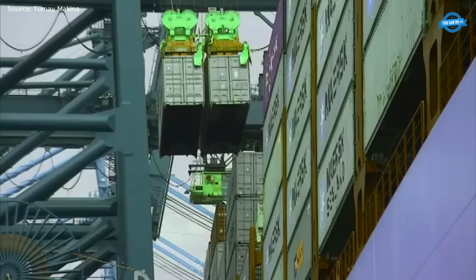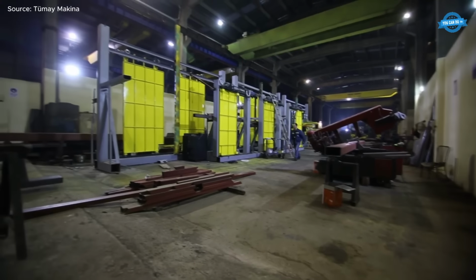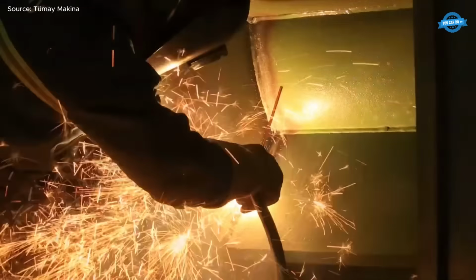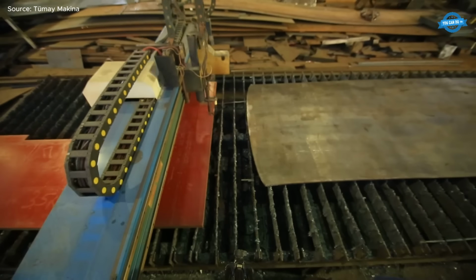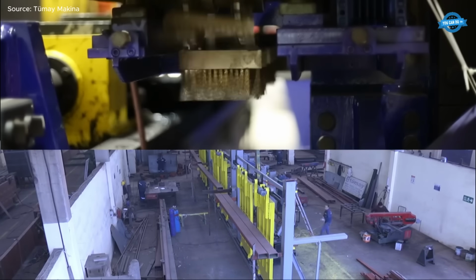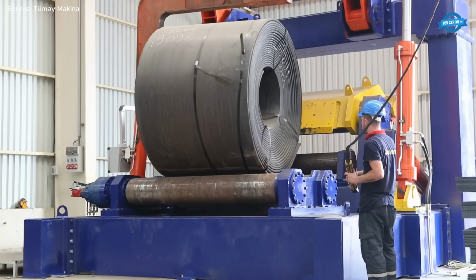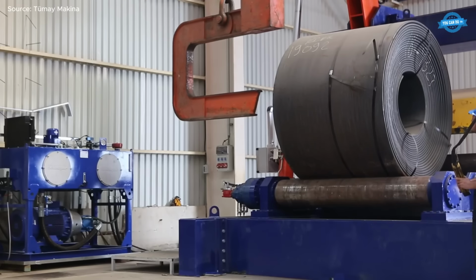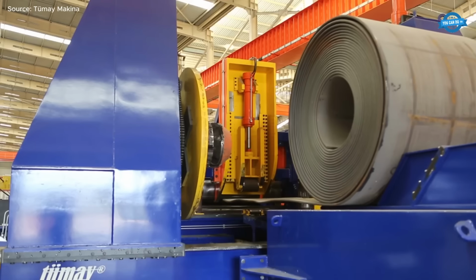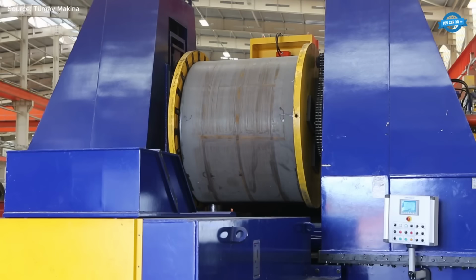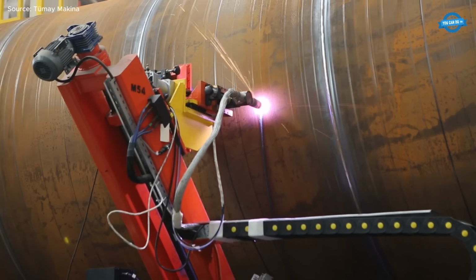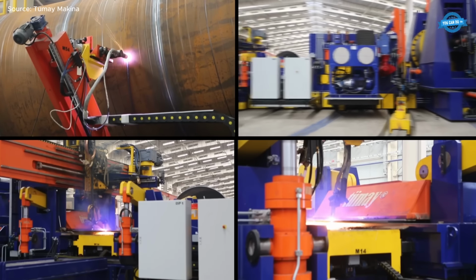In this process, steel strip coils are first flattened and guided through forming rollers that gradually shape the material into a spiral configuration. The edges of the strip are then precisely angled according to the required pipe diameter before entering the submerged arc welding stage. Here, the seam is welded both internally and externally to ensure structural integrity.